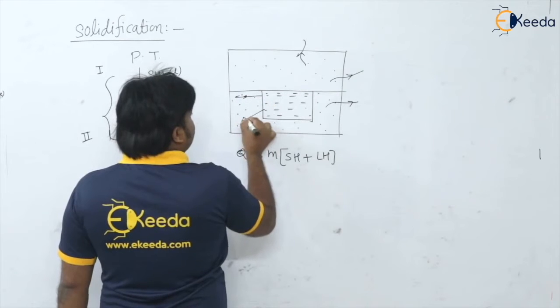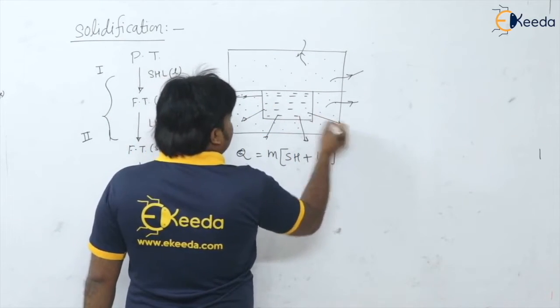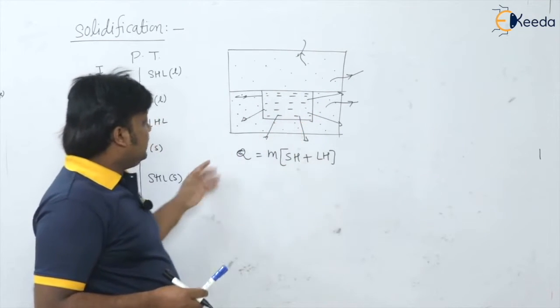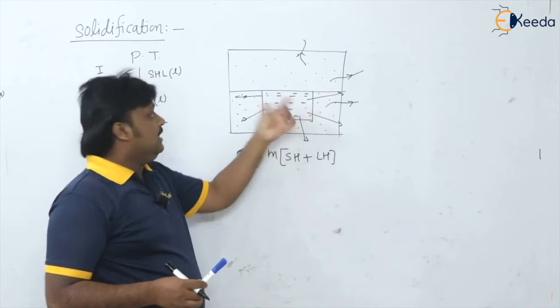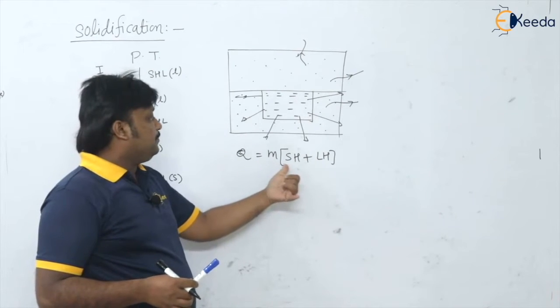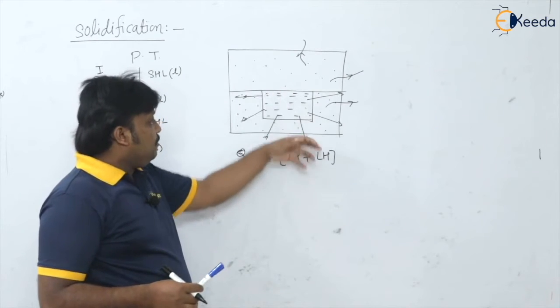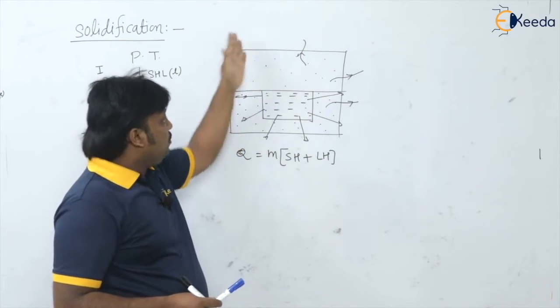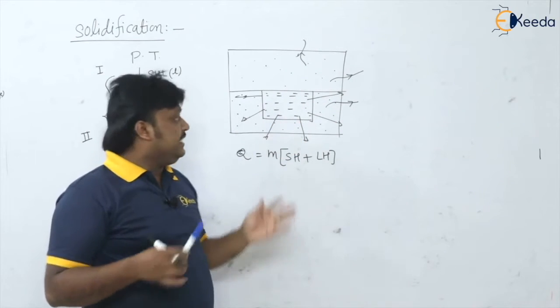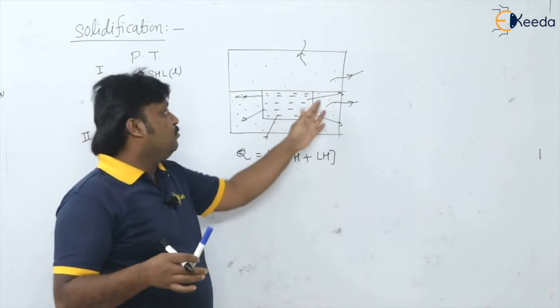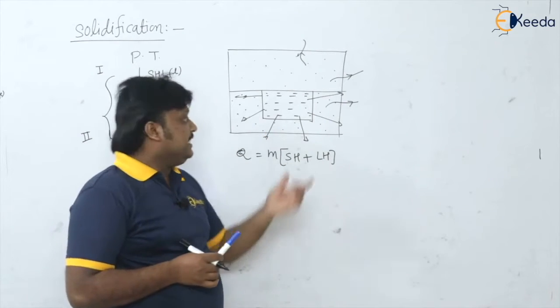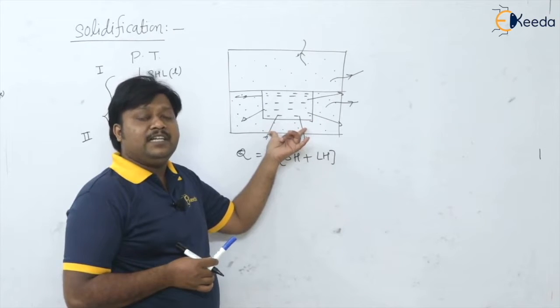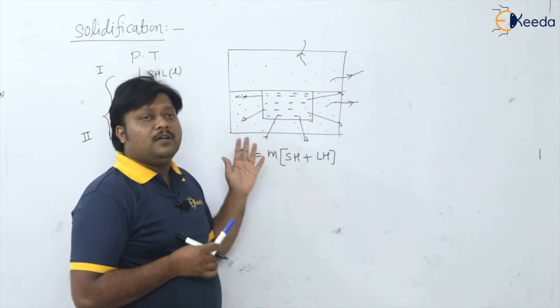From all phases of the mold cavity, heat is transferred to the surroundings. In the first stage, the heat loss by the liquid molten material poured into the mold cavity is mass times (sensible heat plus latent heat). The same amount of heat is transferred from the mold interface — via the sand mold — to the surroundings. The heat transfer equation for this conduction through the mold follows the rule of heat conduction with infinite wall thickness.